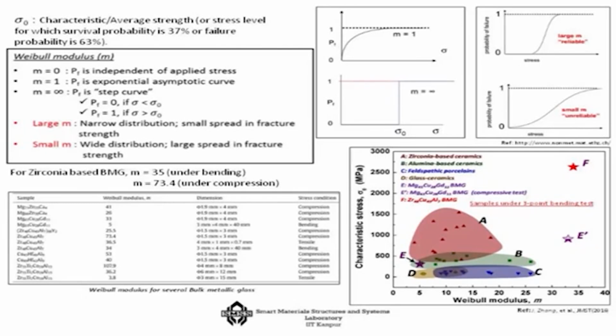Okay. So, these are like bulk metallic glasses, and then somewhere around here you can see zirconia based ceramics, alumina based ceramics, or feldspathic porcelains. And when you talk about usual glass ceramics, you are somewhere with a very low Weibull modulus. So, that is how, for various ceramic materials, the Weibull modulus varies.